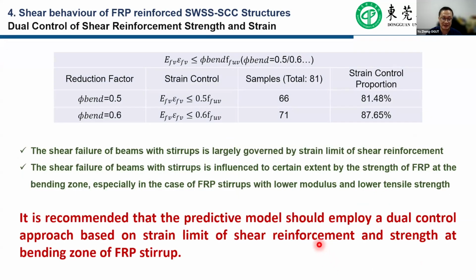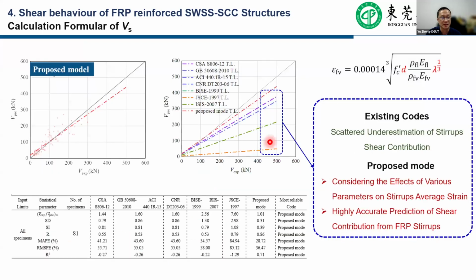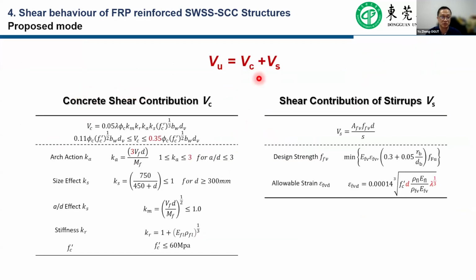And furthermore, for safety consideration, it's recommended to use a dual control approach based on the strain limits for the shear reinforcement and the strain at the bend joint for the FRP stirrup. The two-way control approach will be used. And using this method, we can find that compared to the current design standard, the effective strength of the FRP stirrup can be predicted accurately with our method. After that, we combine those methods together.